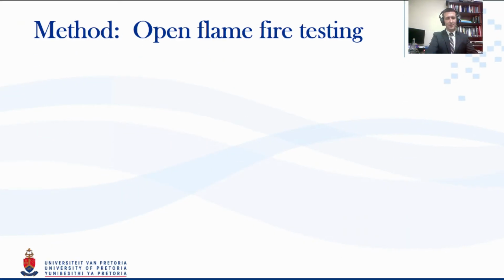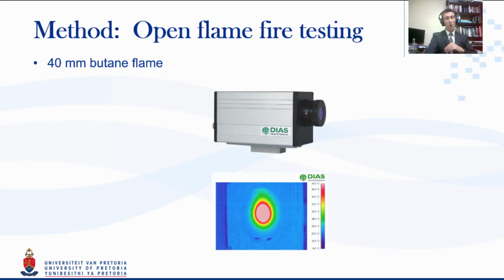So the next thing that we wanted to do is have something in between those two tests. So we had developed an open flame fire testing method, which is coupled with infrared data. One will see there's an infrared camera that we used here. If that is angled at 45 degrees to the flame that is exposed to the material, that keeps the infrared camera safe, but can give you a plethora of information in terms of the thermal behavior during the entire thermal event of open flame exposure.